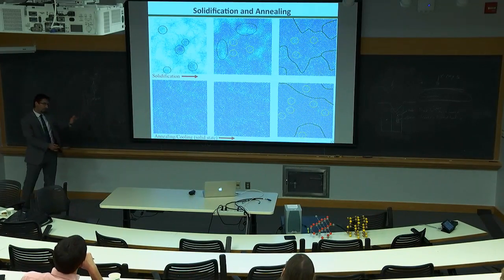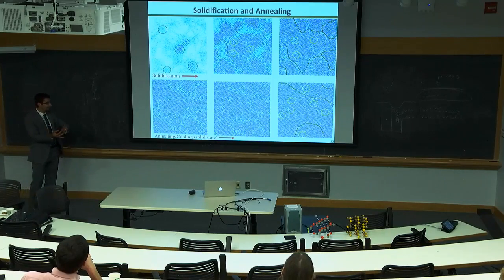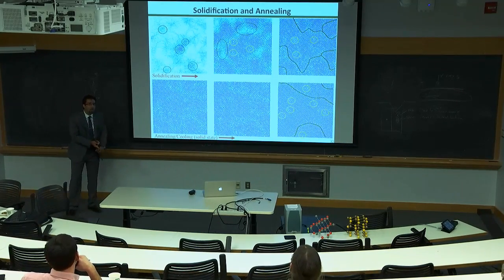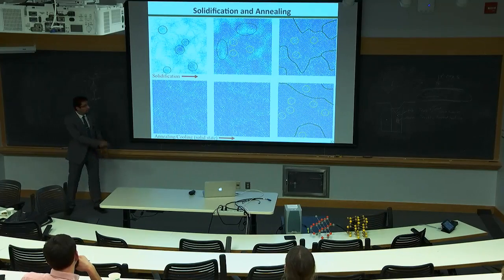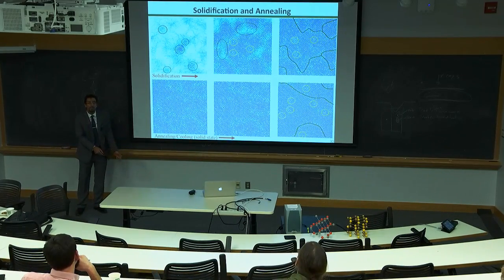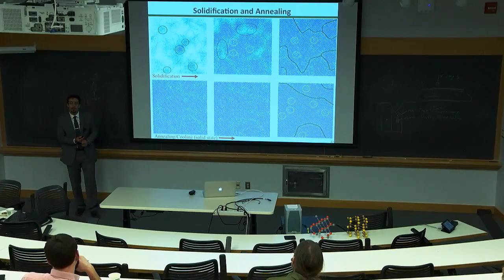So basically, we can simulate elasticity, plasticity, dislocation formation, grain boundary formation, and many different things. This is a density field, similar to DFT. You can deform it. You can get elastic properties out of it. Okay.